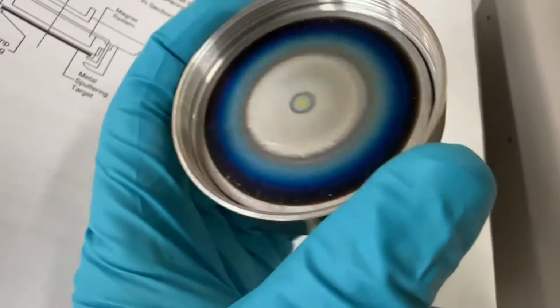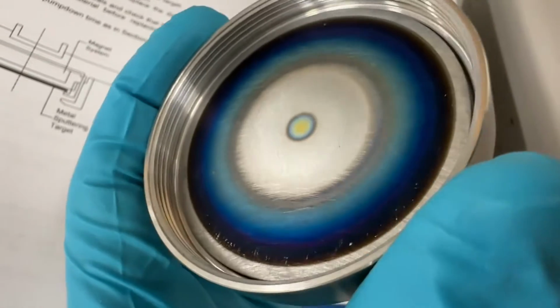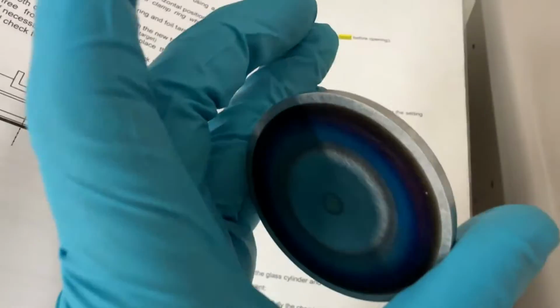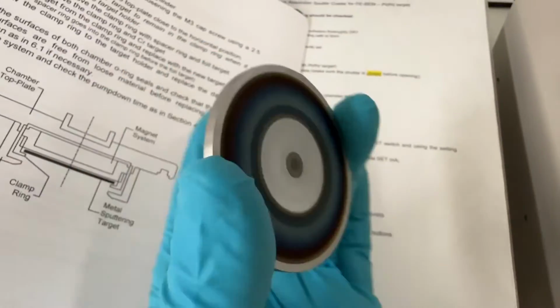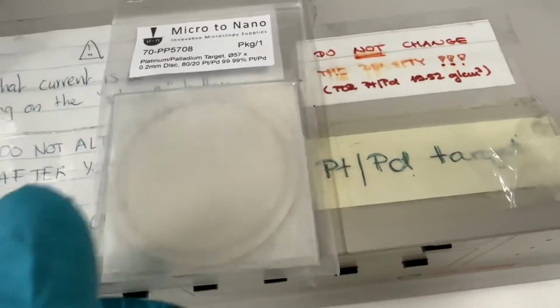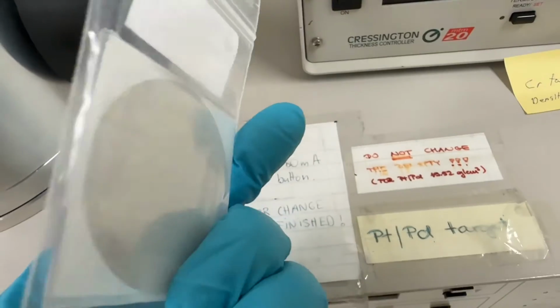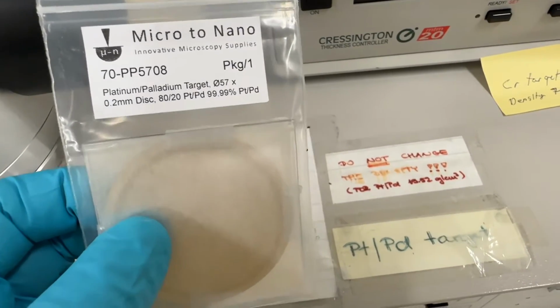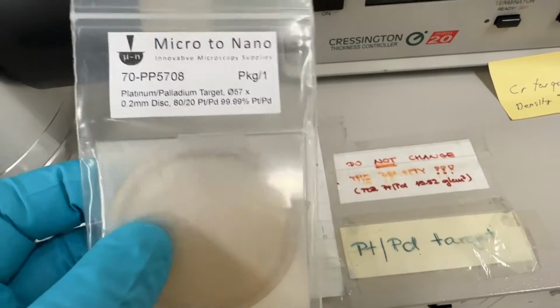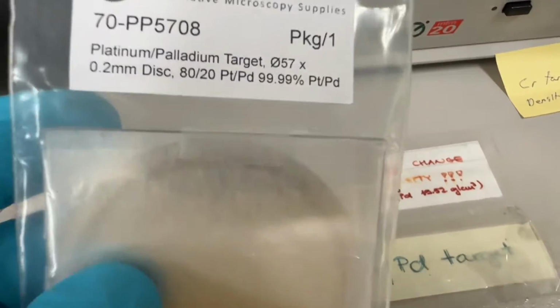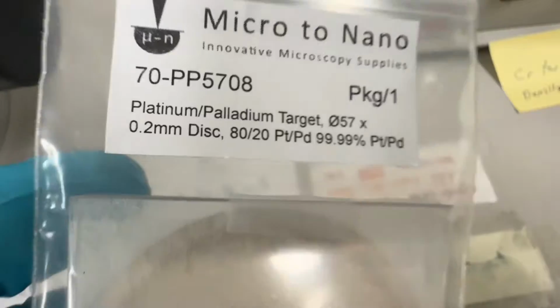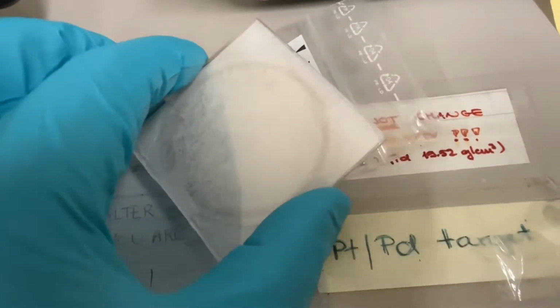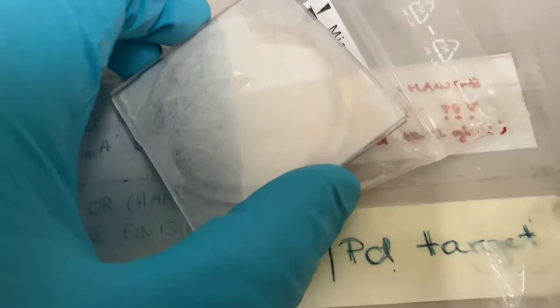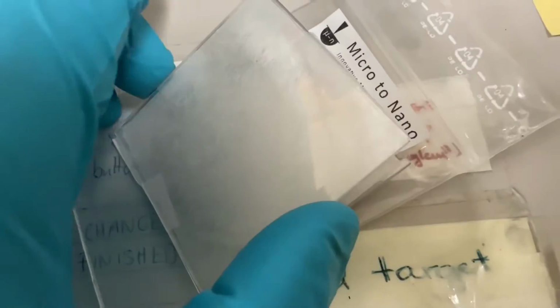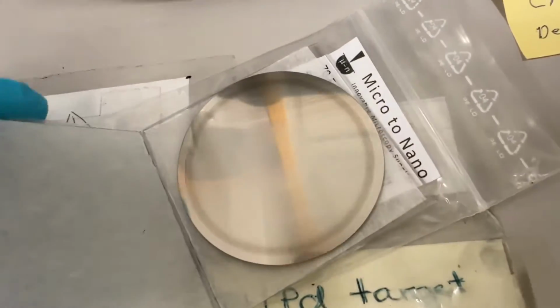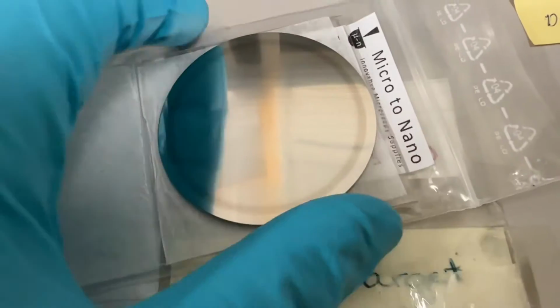So I will now take the target out here and replace it with the platinum palladium target. Here's the chrome target. It's a beefy structure like this. If we're looking at the platinum palladium target, the first thing that will come to your attention is that the platinum palladium target is much thinner. While the chrome target is 5 millimeter, this one is only 0.2 millimeter. A target like this will cost you about 1,000 euros, a little bit more possibly. But this is the mixture of platinum palladium.